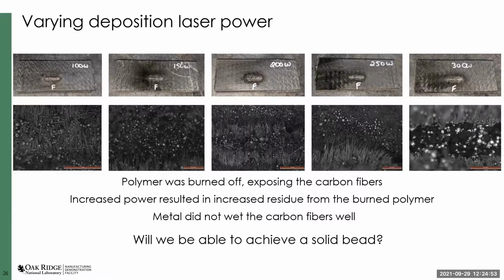You can also see here that with increased power, you get increased residue. So you get almost like a tail of residue that's caused by the smoke. And you can also see it as sort of blackened material on the metal itself. So this is very exciting. It does confirm our hypothesis. However, these aren't fully deposited beads. So basically what we have here is a spray of metal on top of carbon fibers, because as I mentioned earlier, metal does not wet carbon fibers well at all. So the next step was to determine if we could achieve a solid bead.